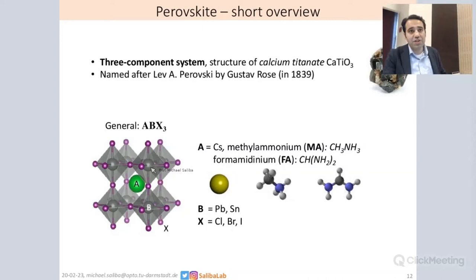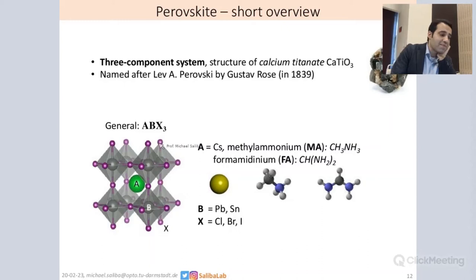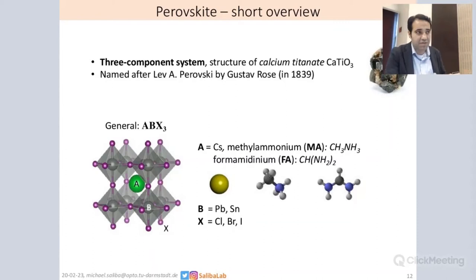Something to keep in mind: the metal halide is usually very important for the electrical properties, much more important than the cation in many ways. This is because they often form covalent and ionic bonds, with a lot of interaction between the metal and the halide. There is less interaction with the cation, and that's also why the cation has a different role from the metal halide cage.